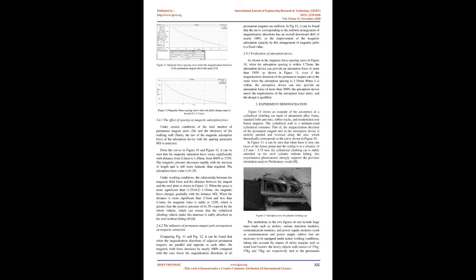2.4 Analysis of simulation results. 2.4.1 The effect of spacing on magnetic adsorption force. Under certain conditions of the total number of permanent magnet units, 20, and the thickness of the walking wall, 5 mm, the law of the magnetic adsorption force of the adsorption device with the spacing parameter mx is analyzed. From the curves in figure 10 and figure 11, it can be seen that the magnetic attraction force varies significantly with distance from 0.2 mm to 1.45 mm, from 800 N to 375 N.